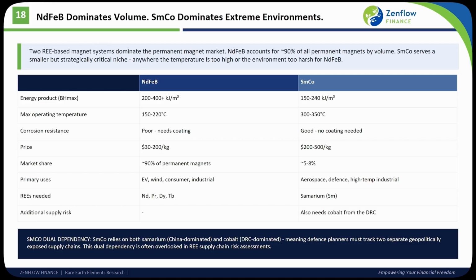SmCo accounts for 5 to 8% of the market by volume, but serves a strategically critical niche. Its energy product is lower, 150 to 240 kilojoules per cubic meter, but its maximum operating temperature is dramatically higher, 300 to 350 degrees Celsius. Corrosion resistance is excellent, no coating required. Price is much higher, 200 to 500 per kilogram. Applications are aerospace, defense, and high temperature industrial uses. The rare earth it requires is samarium.